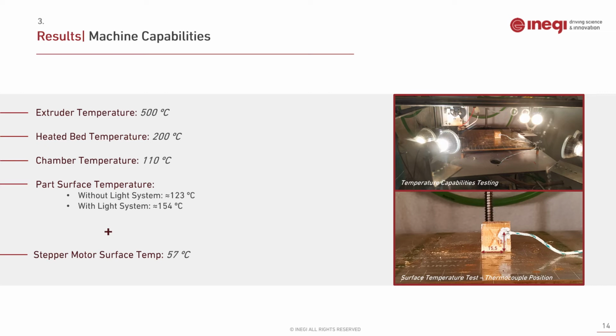Firstly, we'll start by pointing out the achieved machine capabilities in terms of temperature performance. As stated by the manufacturer, the extruder reaches a temperature of 500 Celsius degrees, and the heated bed reaches a temperature of 200 Celsius degrees. The air in the chamber reaches up to a temperature of 110 Celsius degrees. In terms of surface temperature, with the printing conditions of having the chamber at 110 Celsius degrees and the heated bed at a temperature of 200 Celsius degrees, we measured the surface temperature in the part in the position shown in the figure, a temperature of 123 Celsius degrees without the radiation system and of 154 degrees with the light system turned on.